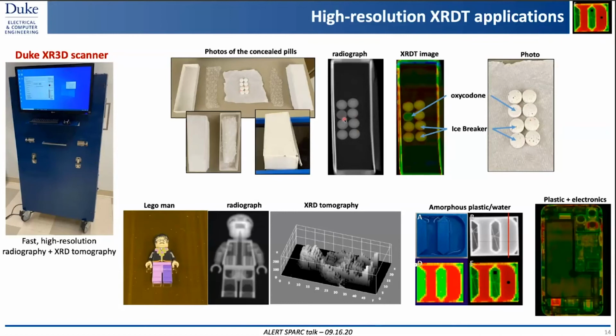And you can see that in the transmission radiograph, there is some slight color difference, but again, it's unclear whether it's due to the fact that the oxycodone is clearly thicker or if it's really the different density of the material. Whereas in the diffraction image, the oxycodone lights up in this green color, which is just a false coloring based on the X-ray diffraction spectrum. So being able to do some drug detection or pill evaluation in this scanner, which takes a minute or two to make this full scan, is something that we're playing around with.